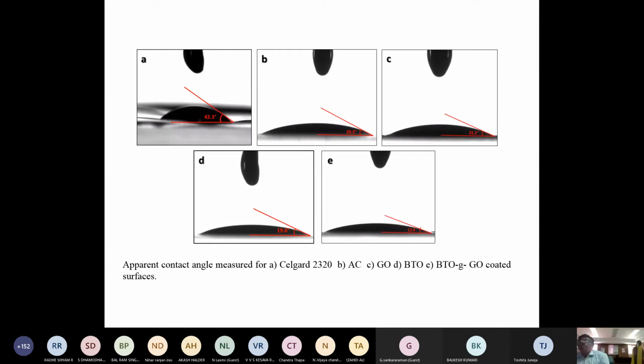And we have measured the contact angle for different systems, because when the contact angle is low, the wettability of the electrolyte is higher. So normally the Celgard membrane, which is made up of polyethylene or polypropylene, has poor wettability and will not soak the electrolyte. So when we coated with graphene oxide and barium titanate graphene oxide, it shows a lower contact angle. That means the wettability is higher.